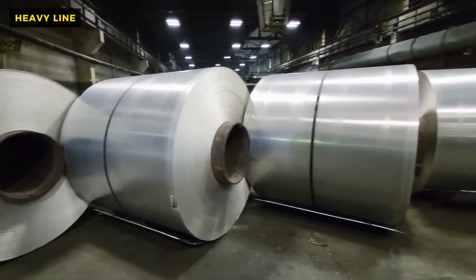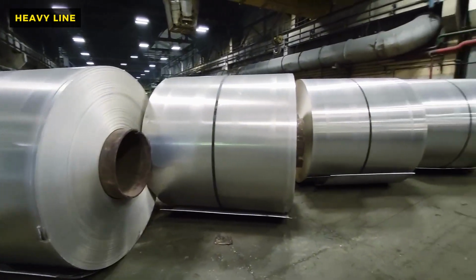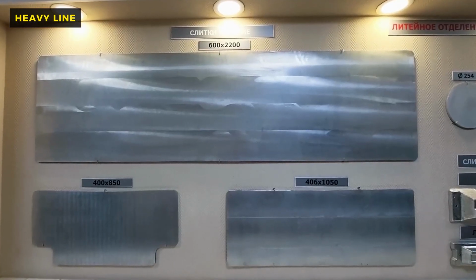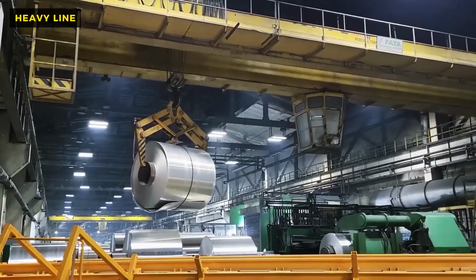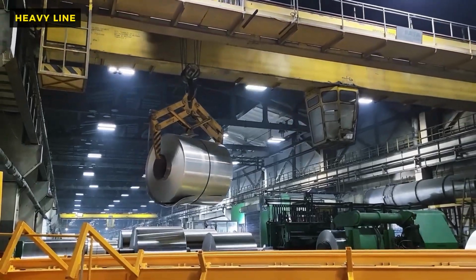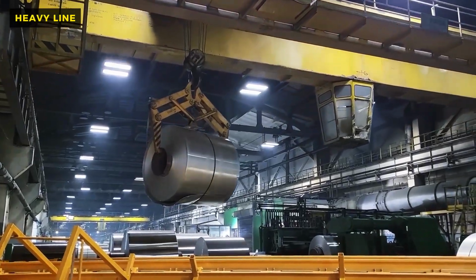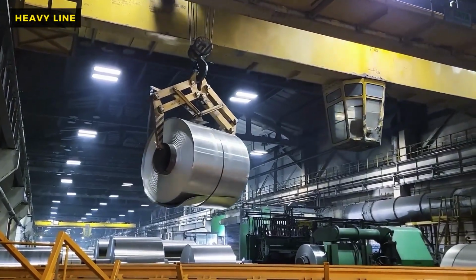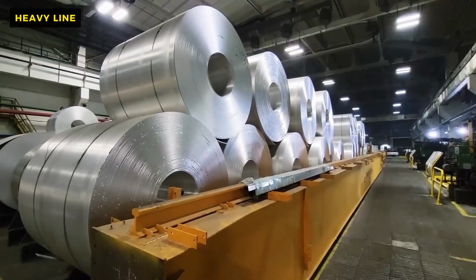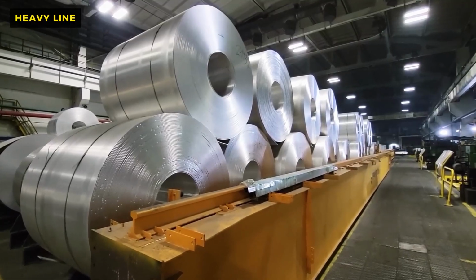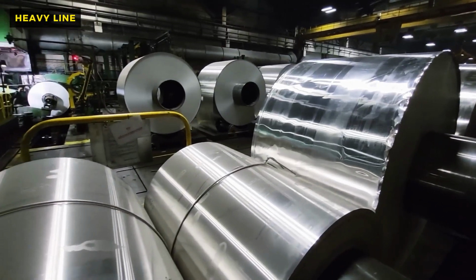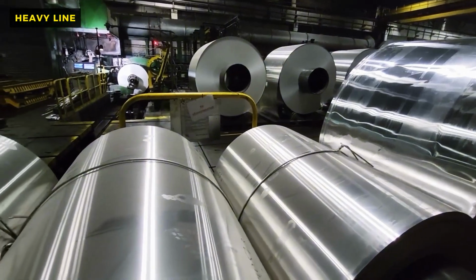The casting process itself is a battle against impurities. As the metal flows, it passes through ceramic foam filters to catch any microscopic inclusions of bath or oxide that could weaken the final product. Even dissolved hydrogen gas, which can cause porosity and bubbles in the solid metal, is removed by spinning rotors that inject inert argon gas into the melt, gathering the hydrogen like a sponge.